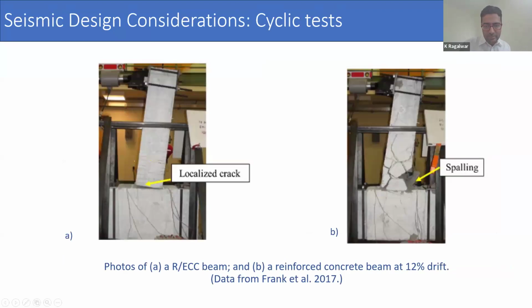So this is another test here. We look at how these beams behave differently. Now, if we focus on cracking behavior in a reinforced concrete beam at large drifts, what we usually see is just a few wide cracks, often accompanied by spalling of concrete cover, which can be seen here in cartoon B. Once that cover is lost, reinforcement becomes exposed and less stable.